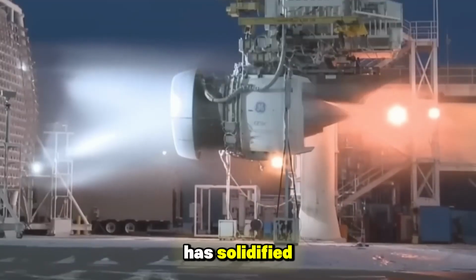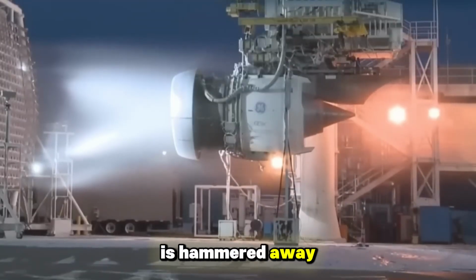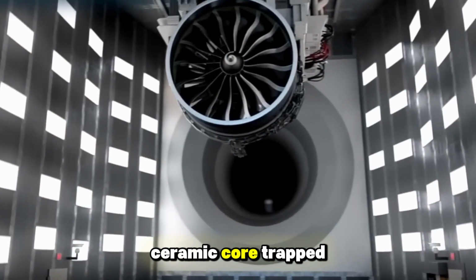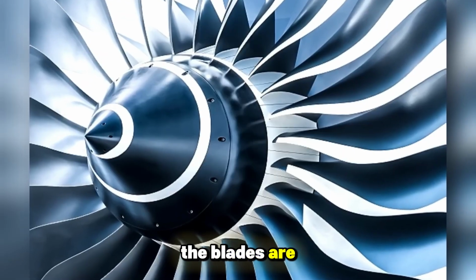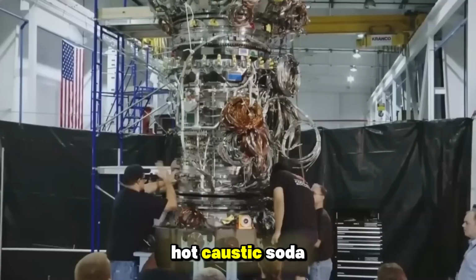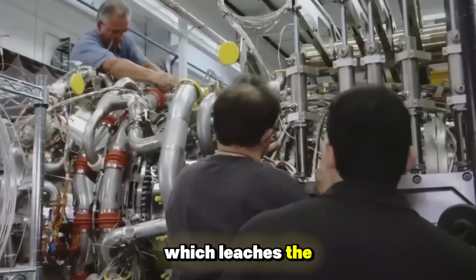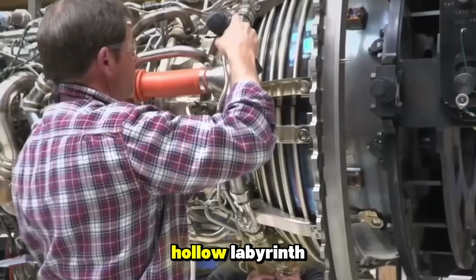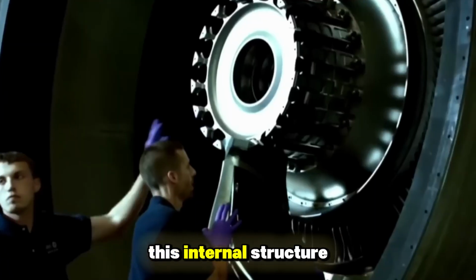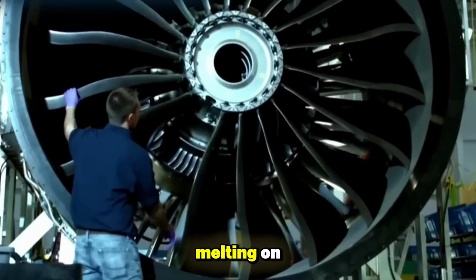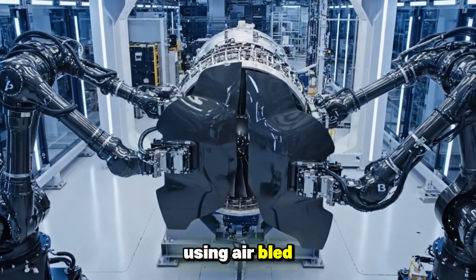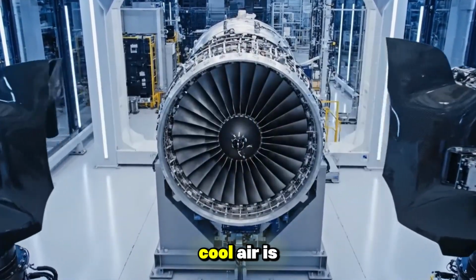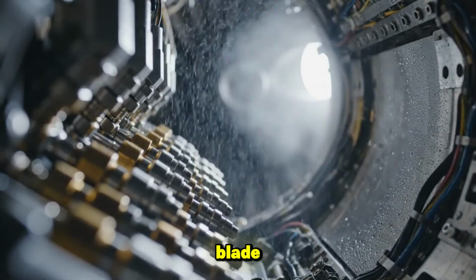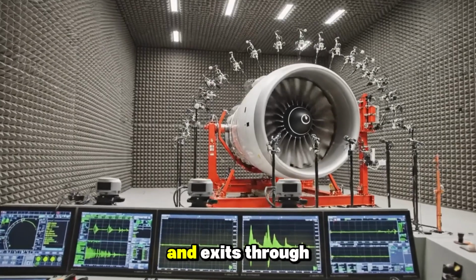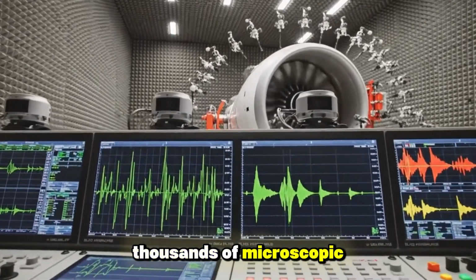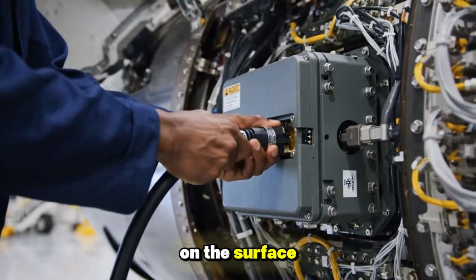Once the metal has solidified, the ceramic shell is hammered away. To remove the ceramic core trapped inside the metal, the blades are placed in a chemical bath of hot caustic soda, which leaches the ceramic out, leaving behind a hollow labyrinth. This internal structure is what keeps the blade from melting. Using air bled from the engine's compressor, cool air is pumped into the base of the blade. It travels through the internal maze and exits through thousands of microscopic laser-drilled holes on the surface.